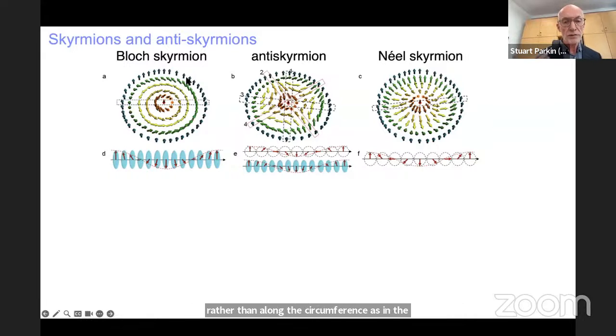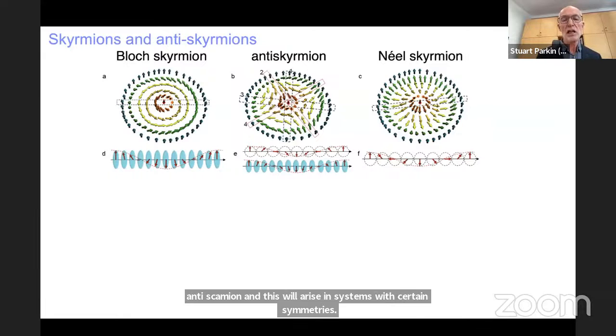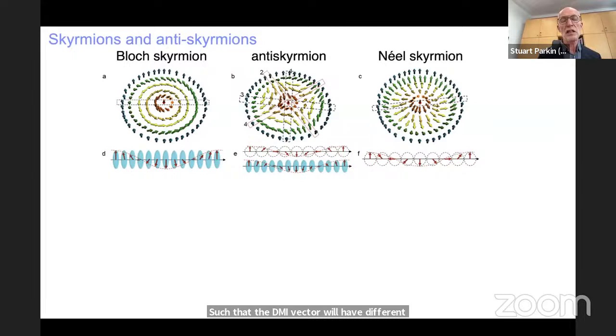A few years ago, it was predicted that there could be, in addition to these two objects, something called an antiskyrmion, and this will arise in systems with certain symmetries such that the DMI vector will have different signs and magnitudes in different directions in the crystal structure. In particular, in certain crystal structures with a certain so-called D2D symmetry, the periphery of this object will now consist of portions of Néel walls and portions of Bloch walls. As you go around the periphery, the red one is the Néel wall, and the black dotted line is the Bloch wall.